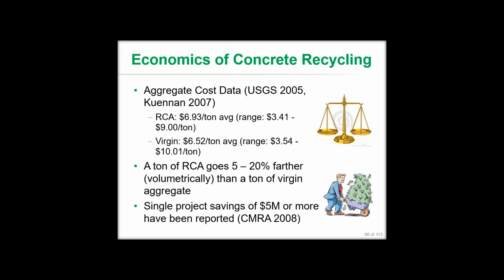So a ton of natural aggregate has, turn it around, a ton of recycled concrete aggregate has 5 to 20% more volume than a ton of natural aggregate. So we tend to do our placements and our uses on a volumetric basis, or our requirements are volumetrically based, I should say. So you can take those costs per ton, but then when you turn it into per usable volume, you're going to see an advantage here on the recycled concrete aggregate side.